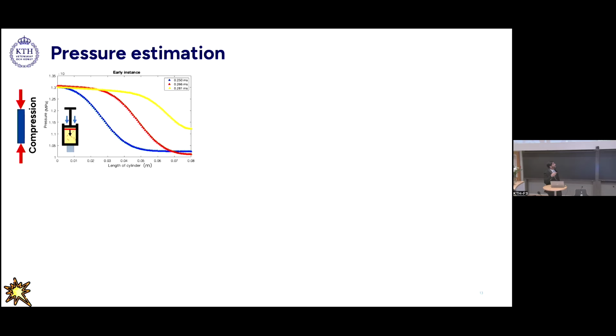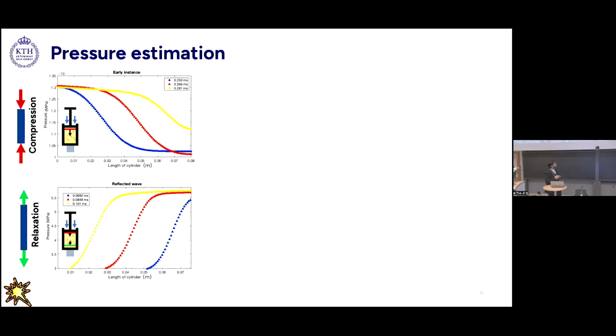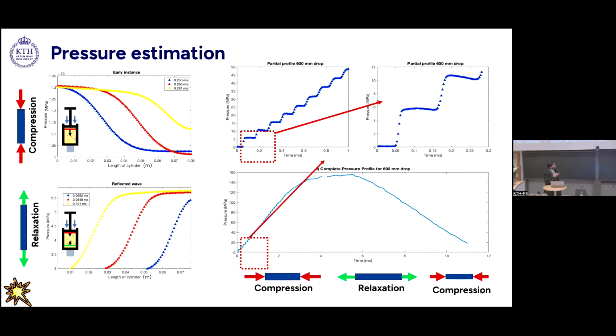If you imagine a cellulose particle in here, then due to the shock wave, it will experience enormous compression forces. And this is the instance where we have isolated the reflected waves. If you imagine the same particle here, after it has passed through the shock wave, it is under compression forces. And when you treat it with the reflection wave, it will experience a little bit of relaxation. As this phenomenon occurs hundreds of times, if you zoom in here, you can see we are getting a stepwise function, and the increment in each step depends upon how the incoming and the reflection waves are interacting with each other. So any particle in this fluid regime will experience compression and tension all together every step of the way, as long as the contact between impactor and the experimental chamber is established.